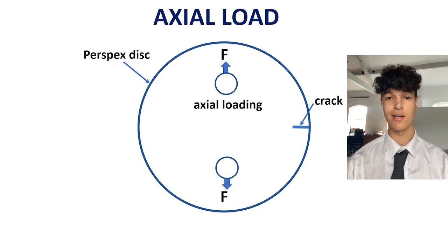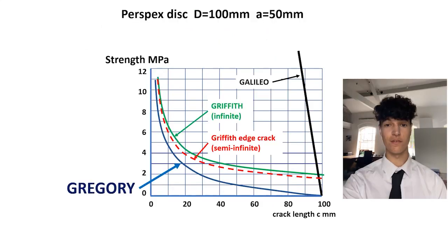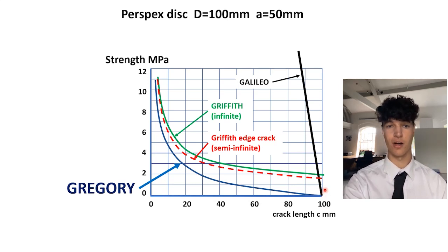First, I calculated the crack equilibrium force for axial loading. The force F is applied along the diameter. The Griffith curve does not fit the facts, and the edge crack solution also does not fit. Here is the nominal strength F over BD, and here is the disc diameter. Meanwhile, the Galileo idea that force is proportional to the area is totally wrong. The Gregory strength goes to 0 when the crack has crossed the disc, which makes sense.